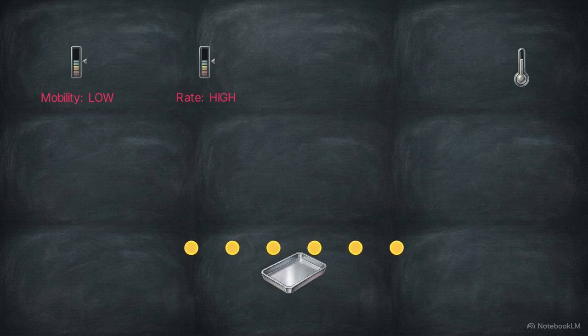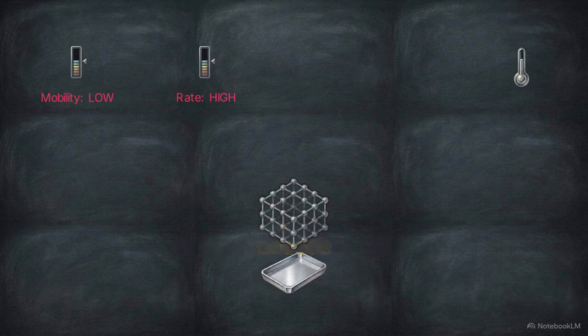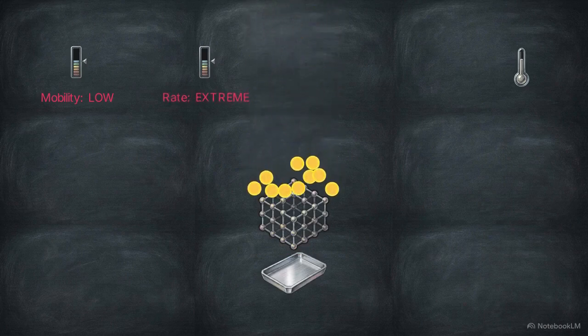Increasing the substrate temperature provides atoms with more kinetic energy, allowing them more time to diffuse and find ideal structural alignments. Conversely, a high deposition rate can overwhelm the surface, burying atoms and freezing them in place before they can find an optimal position. These frozen defects and residual stresses dictate the long-term integrity and lifetime of the coating. The final density of the coating is a snapshot of this thermodynamic and kinetic battle.